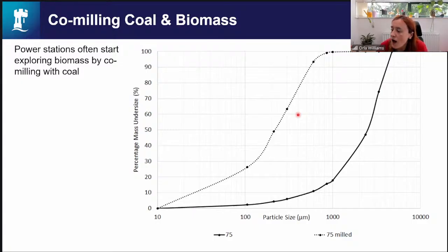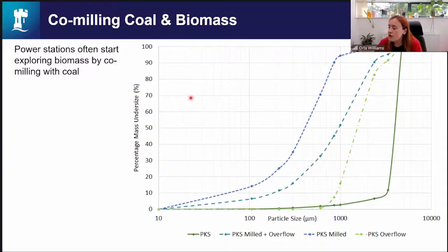This is often a starting point for power stations to look at: can they convert their systems to biomass? And what you see here is the milling of a coal. We're calling it 75, that's just the one we had. You can see here this is the pre-milled size and this is the post-milled size, so you're getting a huge particle size reduction through the milling process. This is the milling profile for palm kernel. The palm kernel original is here, called PKS, and it's very coarse. We then have the milled, which is nice and fine, but we had a significant amount of overflow, which gives us this composite one in the middle.